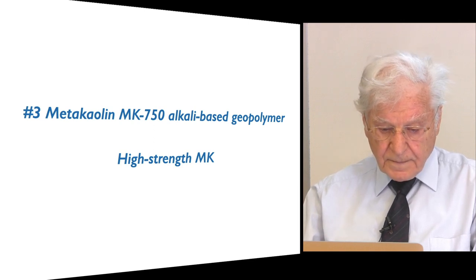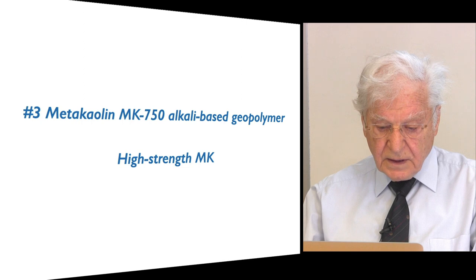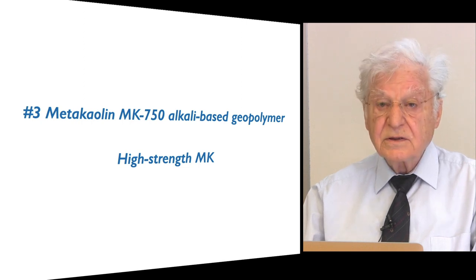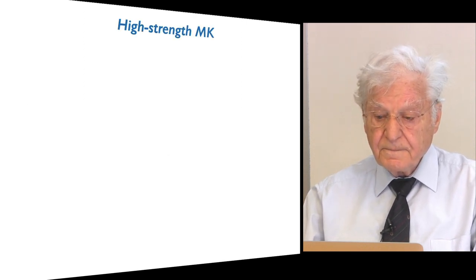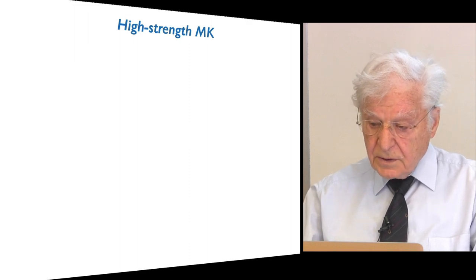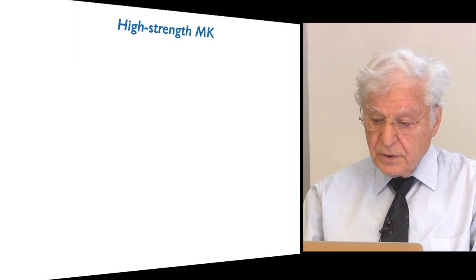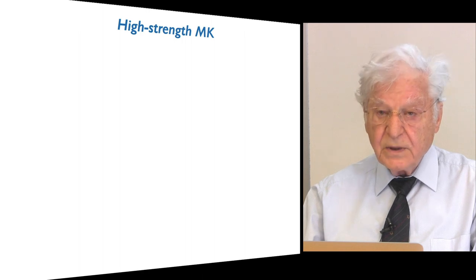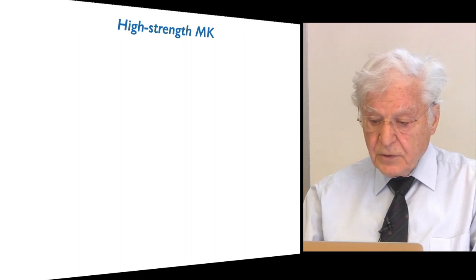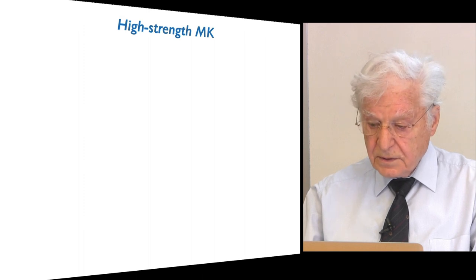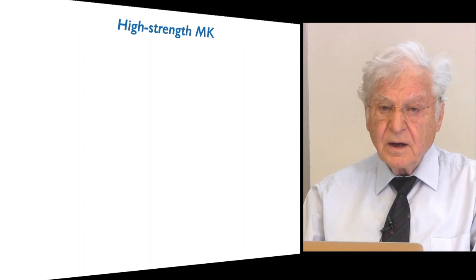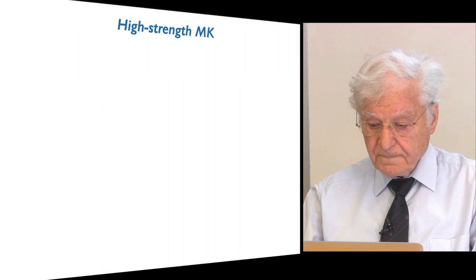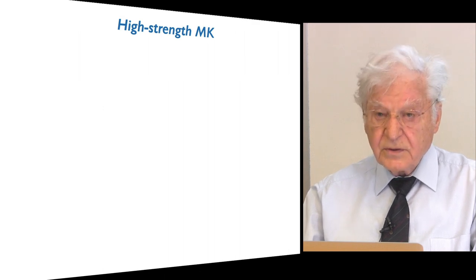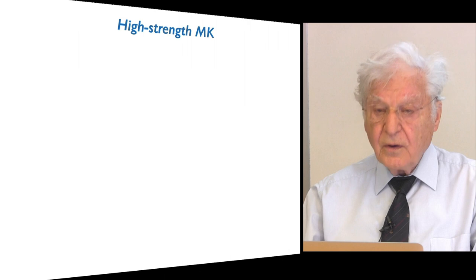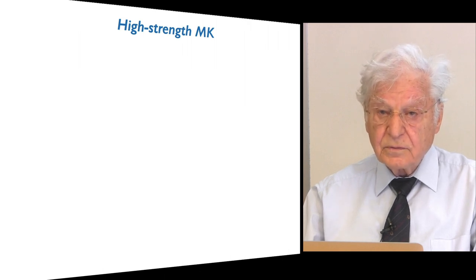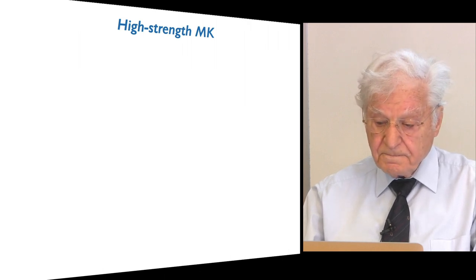Topic number three, metakaolin MK750 alkali-based geopolymer, high-strength metakaolin. During the study and research carried out in our laboratory in the 3D printing of ceramic-like geopolymer, we came across a series of metakaolins which have very high mechanical strength. This was achieved without any additives or the additions of fibers, nothing in it.